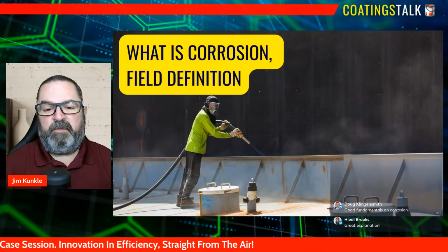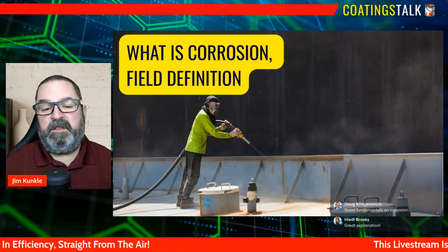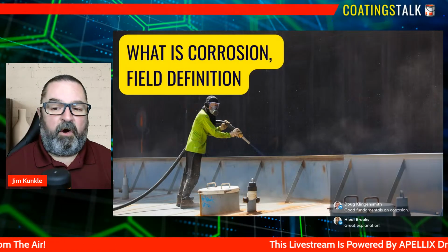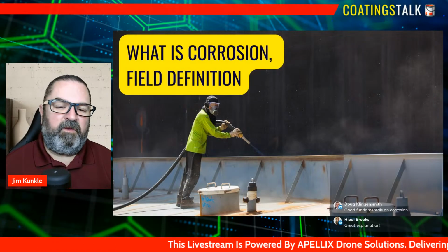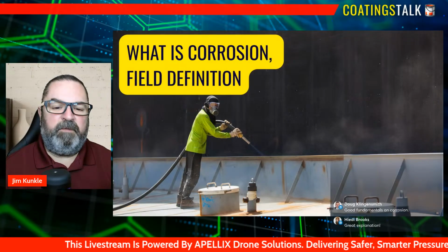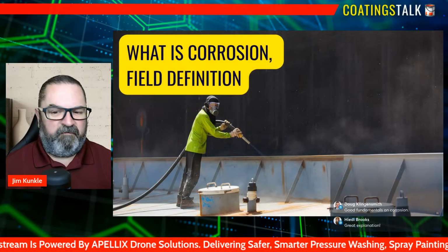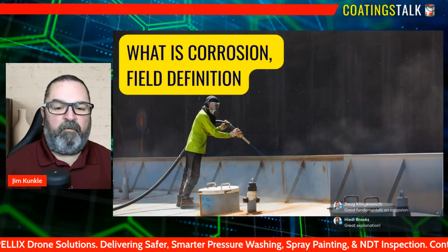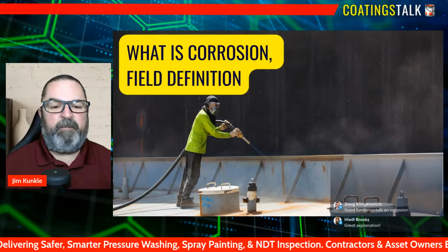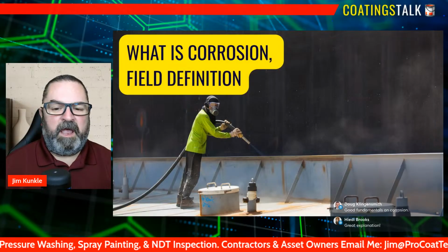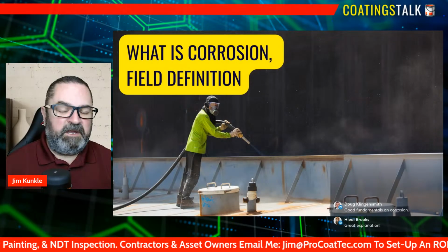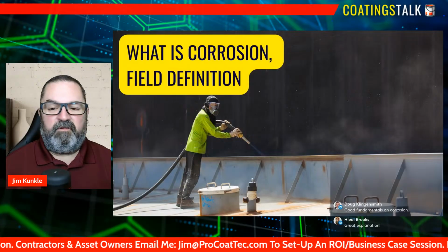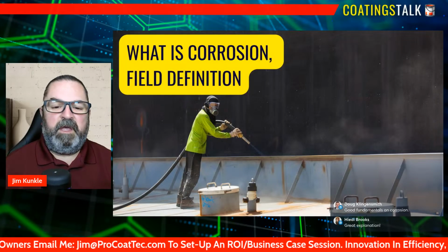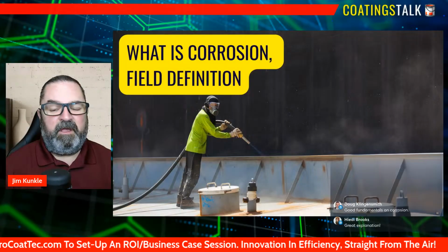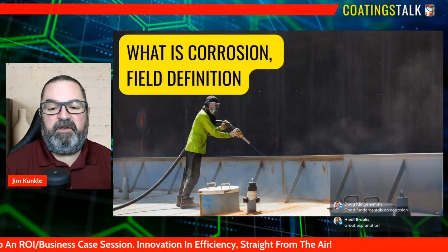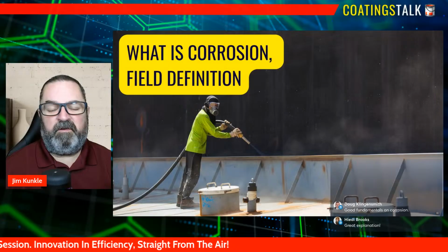Treating rust as a surface blemish rather than a structural warning sign leads to delayed maintenance, hidden deterioration, and ultimately higher risk. Another misconception is that corrosion only matters when it becomes severe or when equipment starts to fail. In truth, corrosion begins long before it becomes obvious. Moisture trapped under insulation, a small coating holiday, or two dissimilar metals touching can initiate corrosion that remains hidden for months or years. Field teams who assume, if I can't see it, it's not happening, often miss the early stage damage that could have been addressed with simple, low-cost interventions.